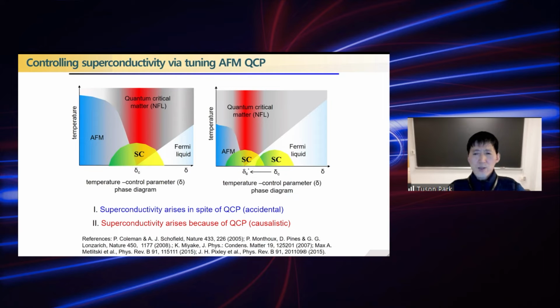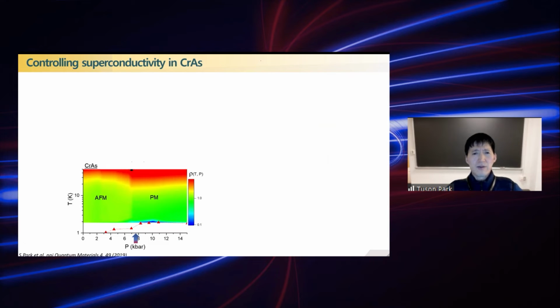So we tested this simple scenario on the binary compound chromium arsenide, which becomes superconducting under pressure. And this is the resistivity contour plot together with the phase diagram. Here, the AFM QCP occurs around 8 kilobar, and the dome of superconductivity is centered around 9 to 10 kilobar. So it's pretty close, making it very plausible that they may be related.